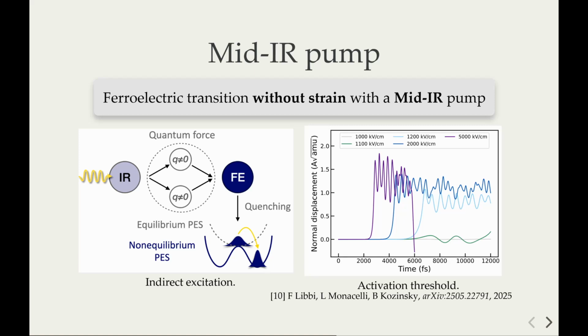We also did a study as a function of intensity, and we see this is an effect that can be switched on and off - if we don't pump with sufficient energy, nothing happens. So this is a highly non-linear response, like a threshold effect. We need a sufficiently high electric field in the pump, otherwise the system does not do anything.